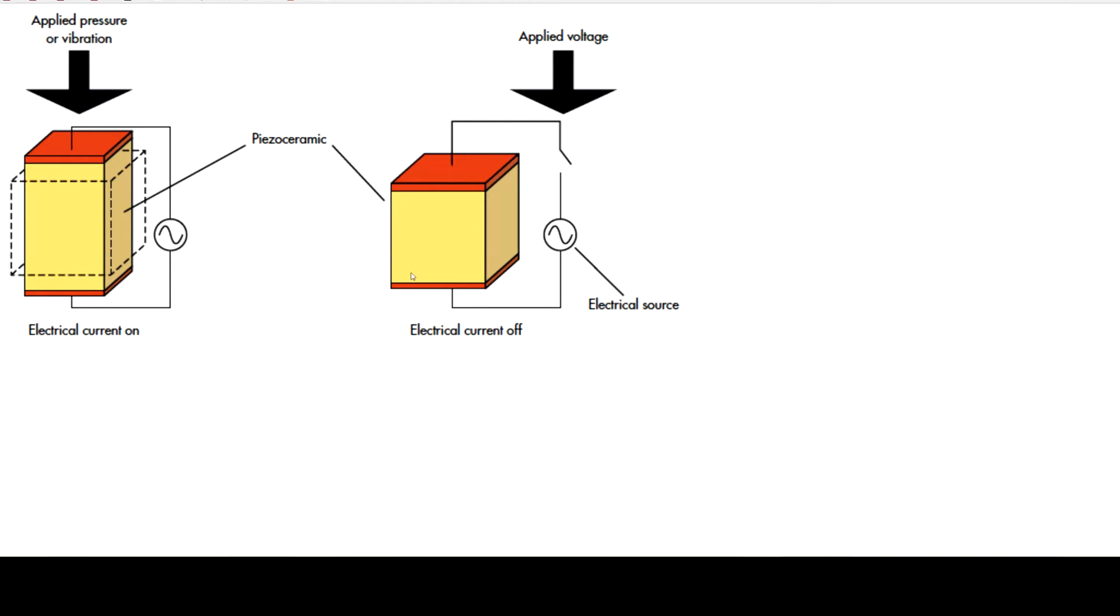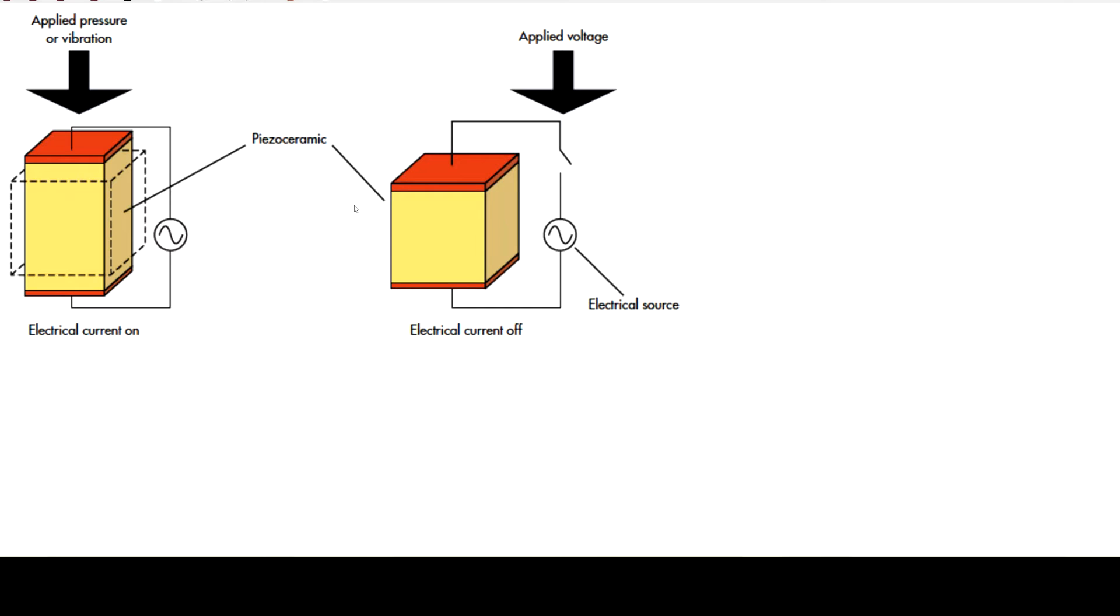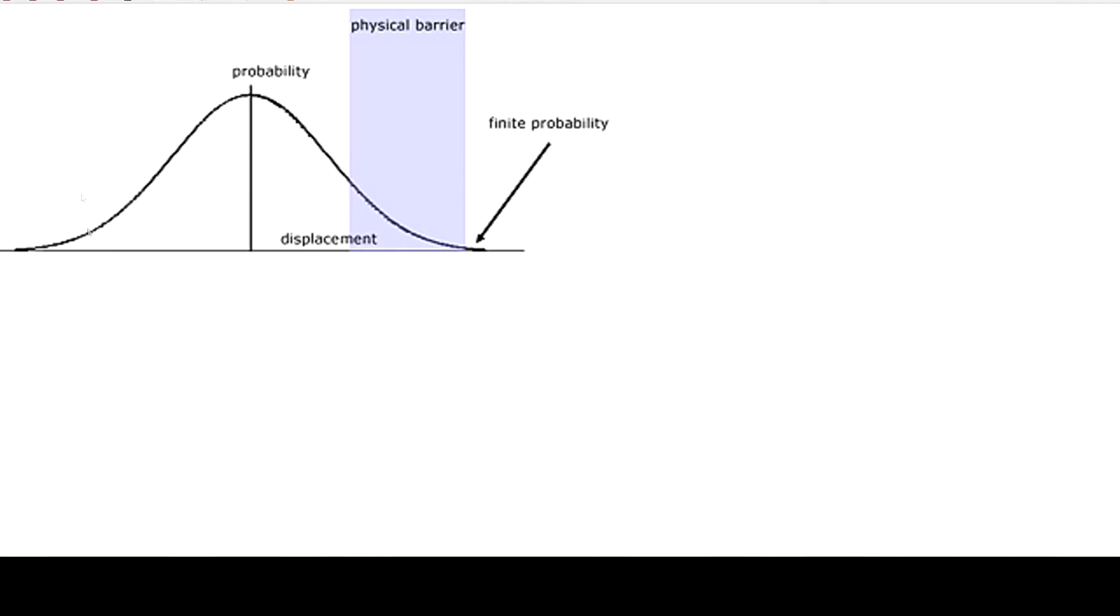The big issue here is that for any material that's a conductor - all metals but also carbon - these materials cannot be compressed that much. They're simply too stiff and if you compress them more they will just crush and not go back to their original state. So why are quantum tunneling composites - they're essentially plastics with an additive that gives them this effect. Why is that such a different effect from the piezoresistive effect? As you can guess from the name, this all has to do with quantum tunneling.